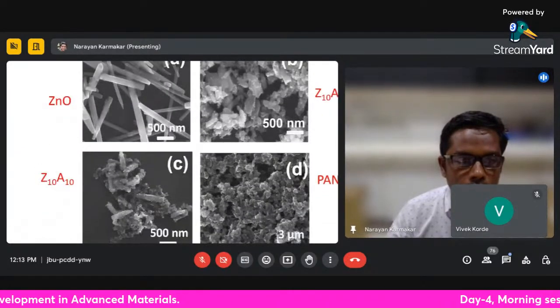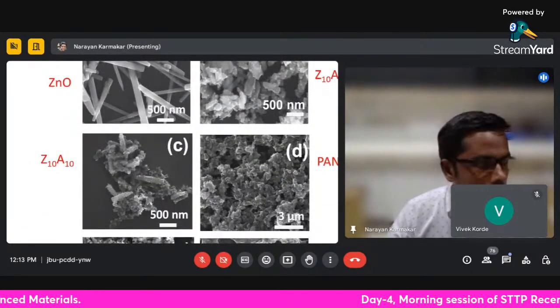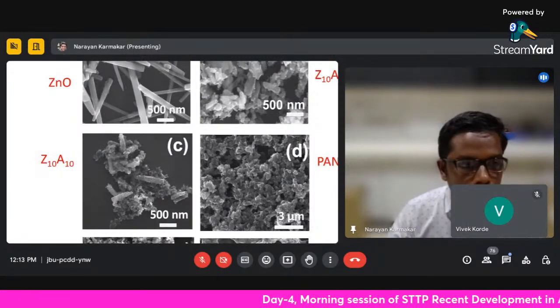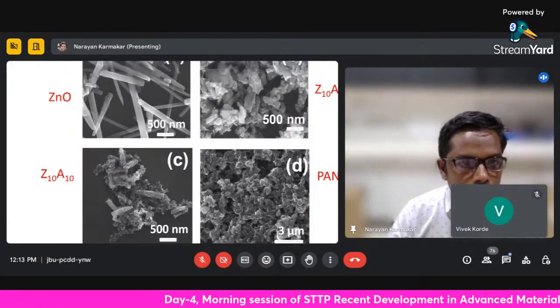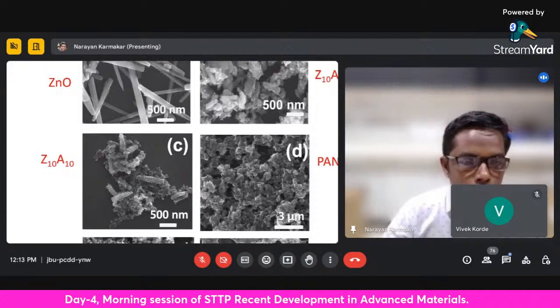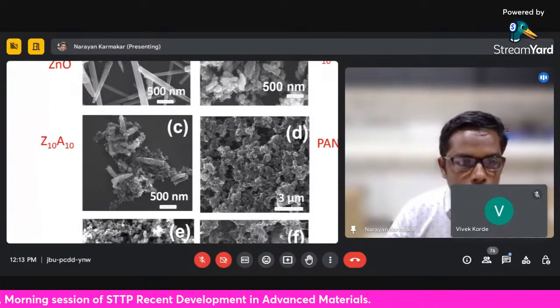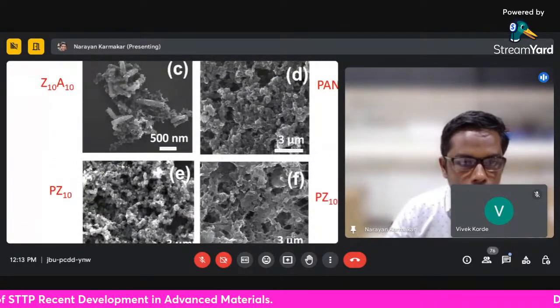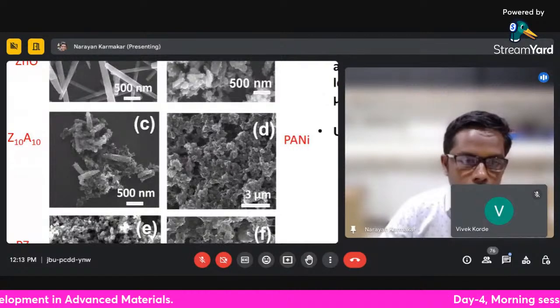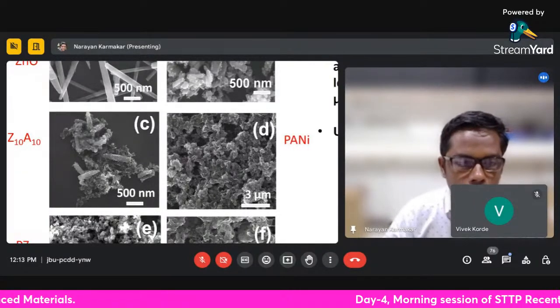Then this is the PZ1018, where we have increased the concentration of the silver nanoparticle. In this case, you can see that agglomeration is forming, where you can see the maximum agglomeration that is forming. And this is what you see in the SEM image of the PANI.